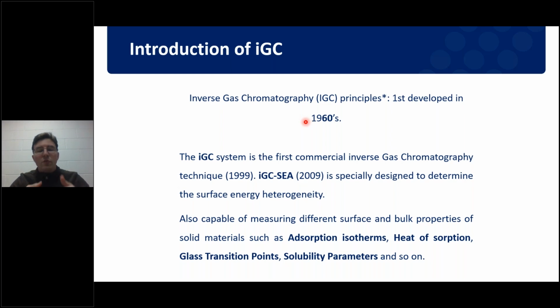Before the commercialization of this technique, these experiments were done on traditional analytical gas chromatography instruments. That means they were not designed to keep the column uniformly heated throughout. They were not designed to inject very well-controlled and small volumes of our gases into the system. And that is what is being optimized in a commercially available unit. It is introducing temperature equivalently throughout your sample. It is introducing your probes in very controlled volumes of injections, and it's ensuring that those probes are injected in the gas phase and not in the liquid phase.